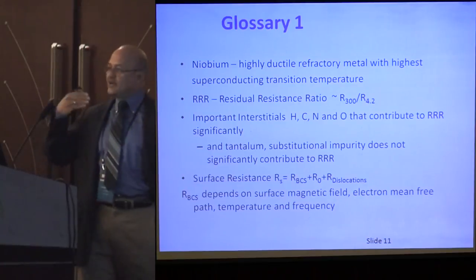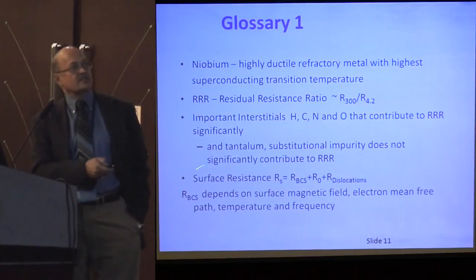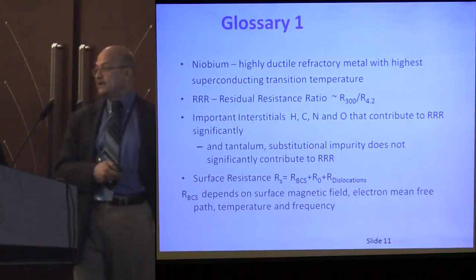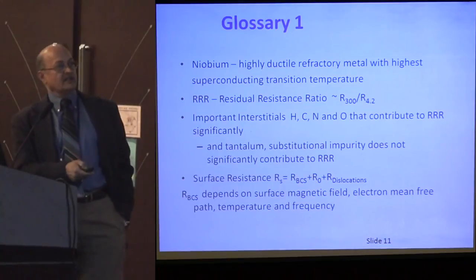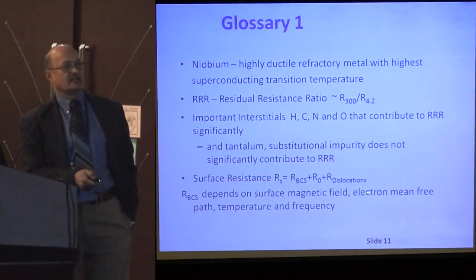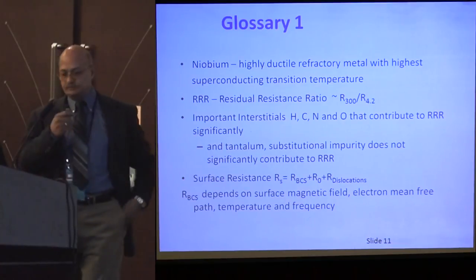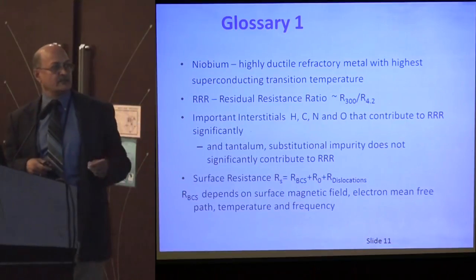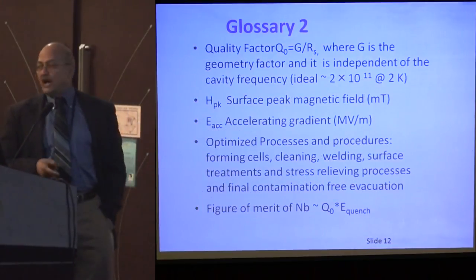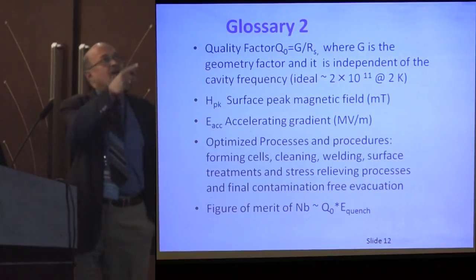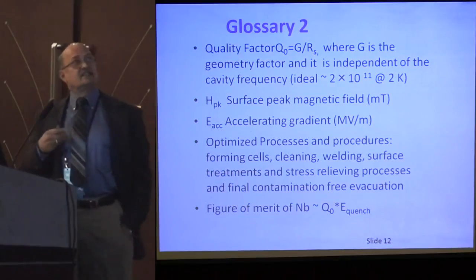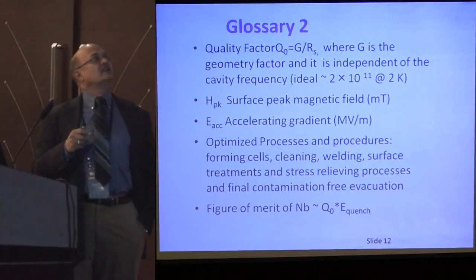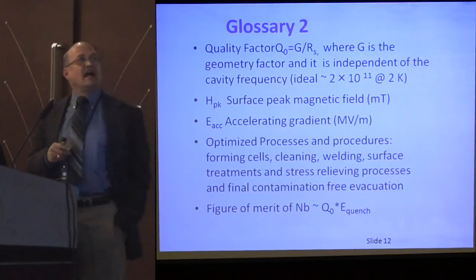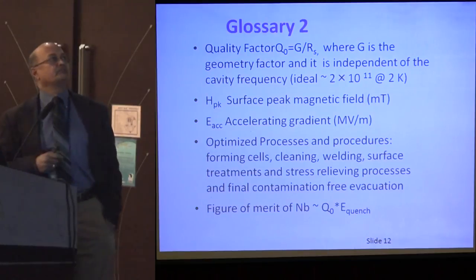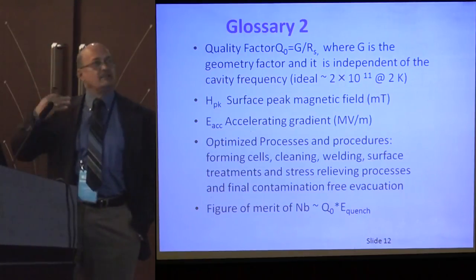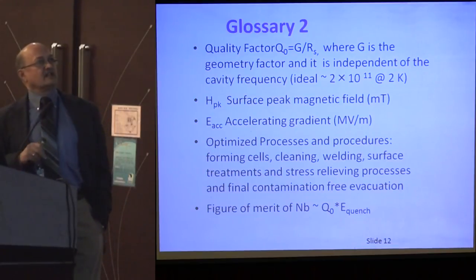The performance of this accelerator structure depends on the surface resistance of the niobium material at the operating temperature, which is 2K basically. It consists of the R_BCS, the residual resistance, and the resistance due to dislocations. The R_BCS depends on the surface magnetic field, electron mean free path, temperature, and frequency. The quality factor of the cavities, as I mentioned, depends on the geometry factor and the surface resistance, where the geometry factor of the cavities used in these accelerators is independent of the cavity frequency, and ideally it could be something like 2 times 10 to the power of 11 at 2K. The surface magnetic field is the one which is limiting the performance of these cavities and also the accelerating gradient. These are related.